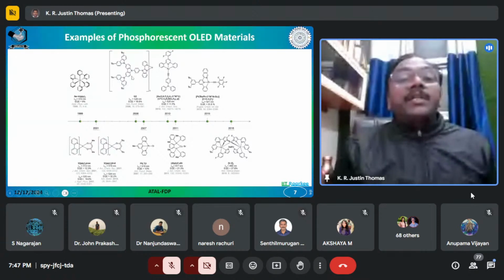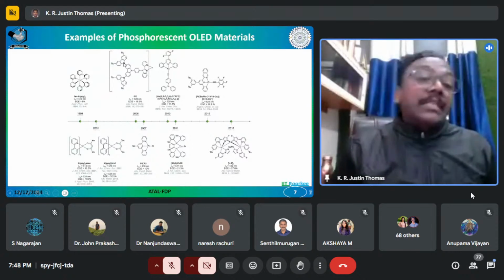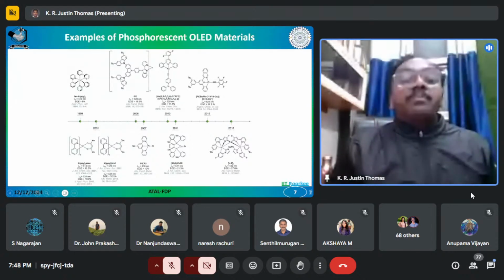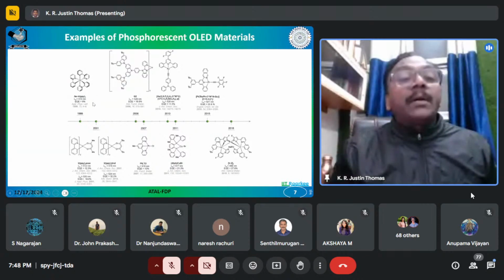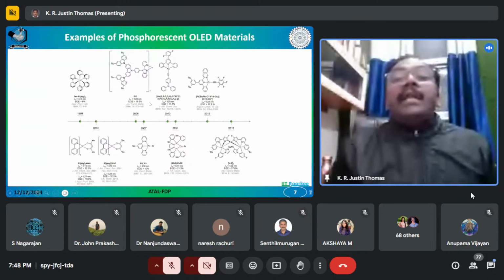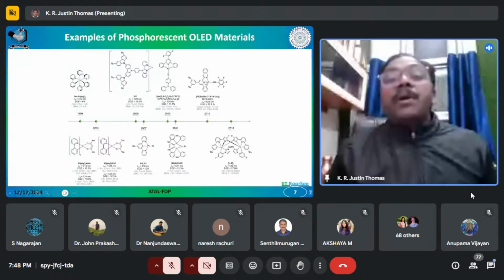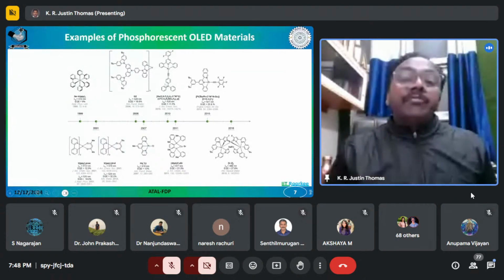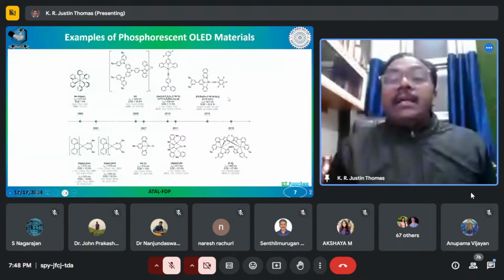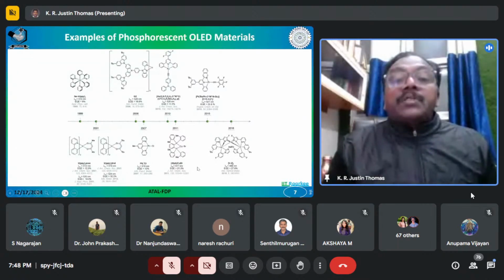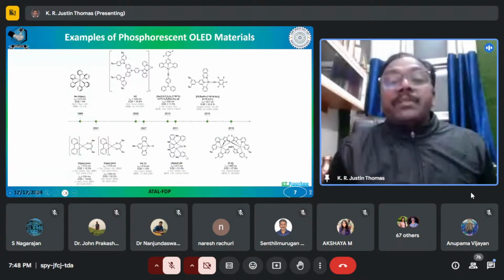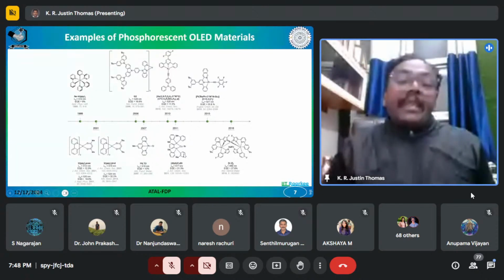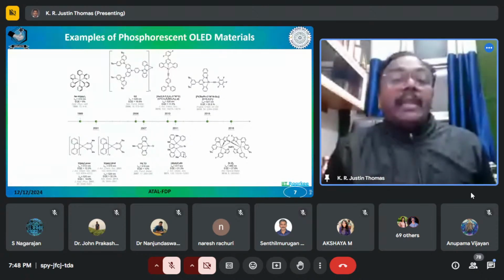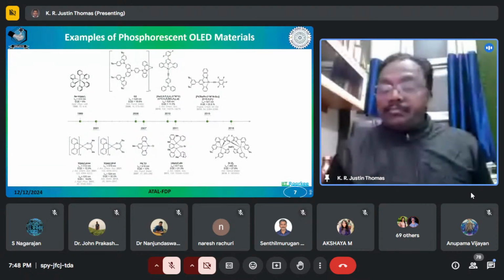For example, in this one, the hole transporting ability of this complex was enhanced by introducing carbazole, which is known to be a very good hole transporter. And then the external quantum efficiency nearly doubled from 8% to 16%. And later people found that gold and platinum complexes can also be used as phosphorescent materials. Okay, and then a copper complex was also reported in 2011 as a phosphorescent material, giving an efficiency as high as 21.3%. Okay, so they can give very good efficiency provided they are used in a polymeric matrix.